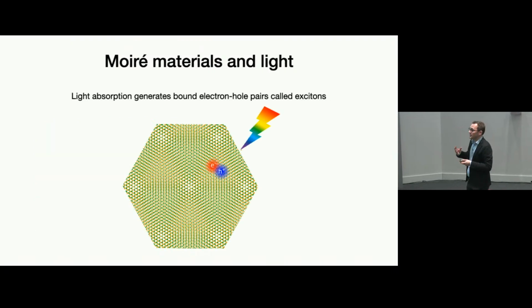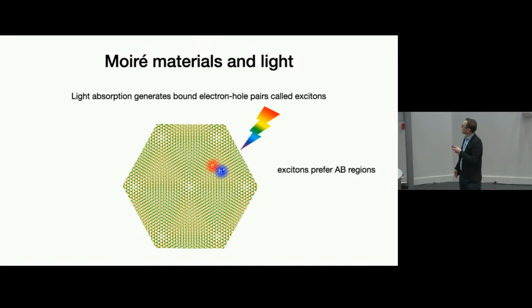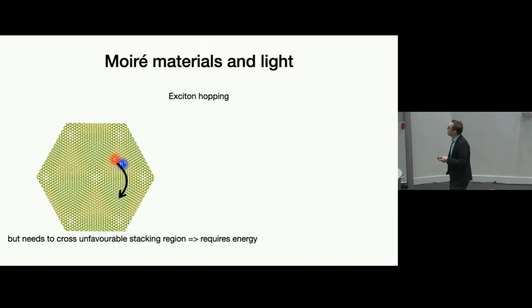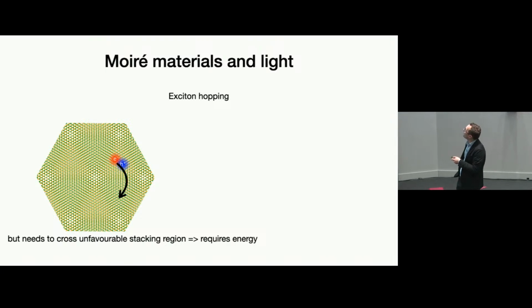Well, what happens is that the light gets absorbed sometimes, and this absorption happens through the creation of a bound electron-hole pair, which we call an exciton. These excitons also prefer to localize in certain regions of the Moiré pattern, and it turns out, in this case, they prefer the AB stacking regions. Once they're created, these excitons can also move around, and what they can do is hop from one AB region to another AB region, but in order to do that, they have to cross an unfavorable stacking region, and that costs some energy.